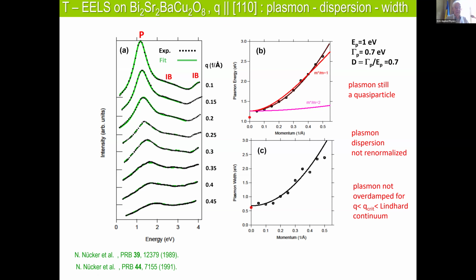And here we see the dispersion and the plasmon widths, and we see well-pronounced plasmons up to about 0.5 inverse angstrom, close to this critical wave vector where the plasmon dispersion merges into the Lindhard continuum.